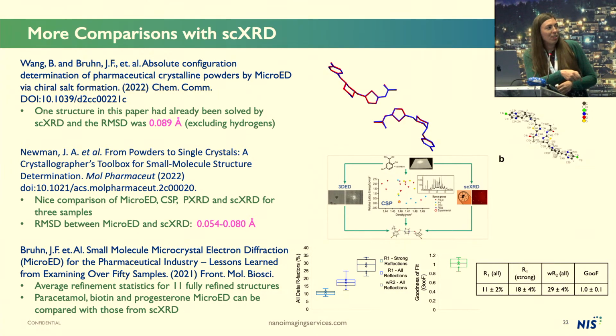Another great paper just came out from Merck, using some of our data, comparing microED, CSP coupled with powder diffraction, and single crystal. They looked at 3 structures in that paper, and the RMSD between our microED structures and their single crystal are very, very low. And then this is another paper that I've published with aggregate data from a bunch of structures we've solved, showing what sorts of R values and things you should be expecting out of a good quality microED structure.